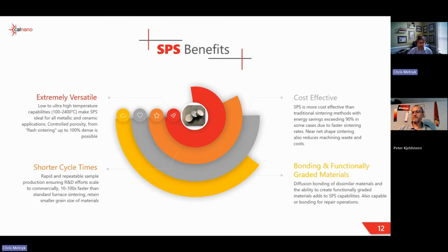Now, fast forward, California Nanotechnologies has 4 SPS units that range in capability from a few millimeters all the way up to 300 plus millimeters. We have the largest commercially available SPS tool in North America, made by Dr. Fritsch out of Germany, called the MSP5. It's a wonderful machine, and we love it. We say 17 inches, of course, in American units, but 300 plus millimeters is kind of the range there. That's also dependent on the material you're doing and the pressure you need. It's a 500-ton press with 85,000 amps of current. So 85,000 amps.